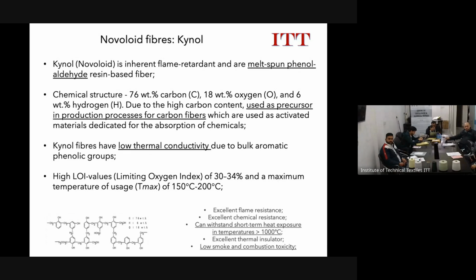Kynol is an example of novolac fiber. We have just secured 50 kg of this fiber, so we will be making yarn by blending with different materials. But the best part I like about Kynol or novolac fiber is that it is 76% carbon. So after converting this fiber into fabric, we can look into making semi-carbon fabric with certain applications, and that will be very interesting. So again, a very interesting fiber to play with and look into.